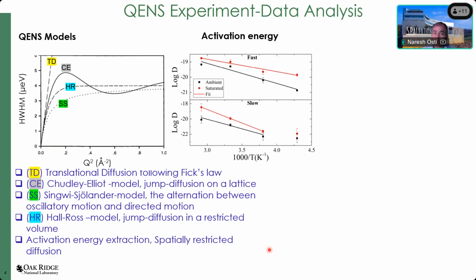Now, once you perform the quasi-elastic neutron scattering, as I said before, you extract the width of that quasi-elastic peak, and then you plot it as a function of the square of the momentum transfer. Depending upon the nature of the Q-squared dependence, you can use different types of model functions. But at the end of the day, you get the diffusion coefficient of all those dynamic processes. And once you get the diffusion coefficient, you can plot that as a function of the inverse of the temperature, from which you can extract the activation energy.